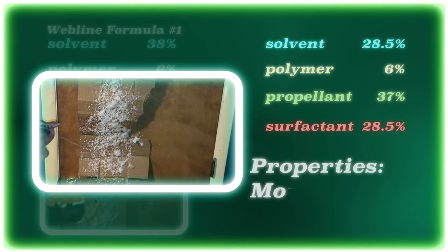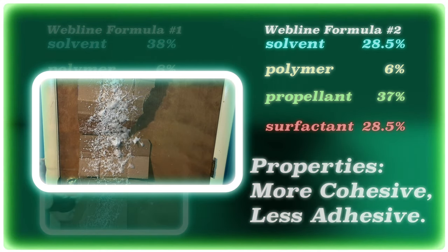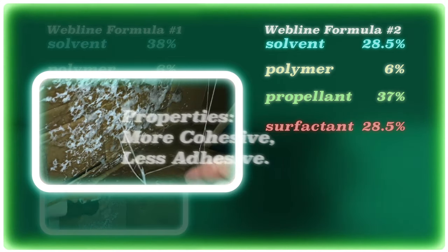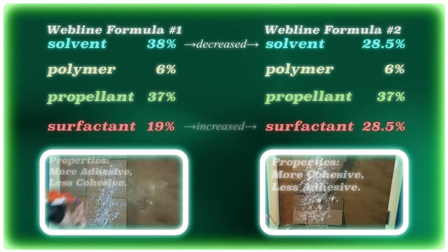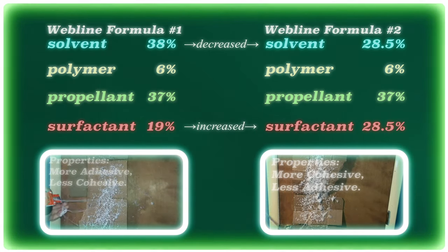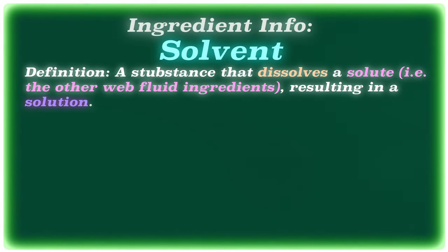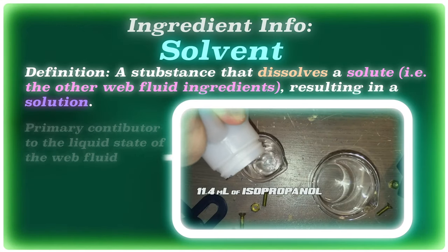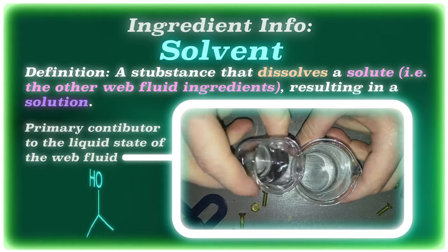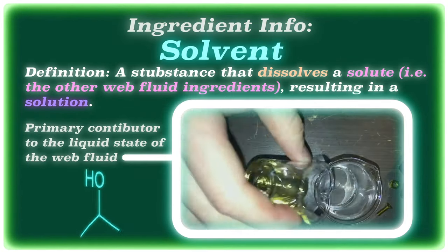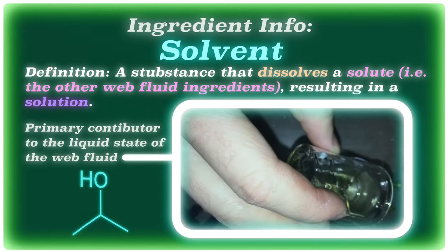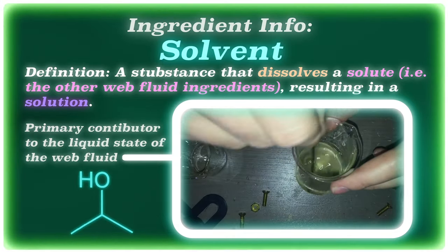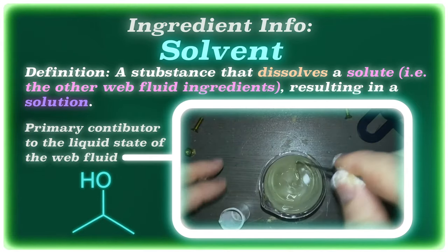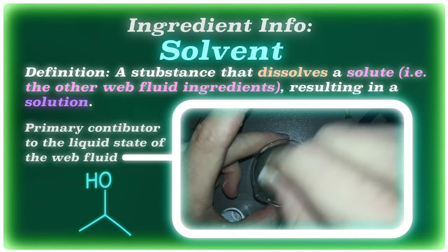I tested this web formula in this video, and it was clear the web lines were slightly stronger. Having the same amount of solvent and surfactant seemed to balance adhesion and cohesion. Why is this? Well, a solvent is what makes the web fluid a fluid for the most part. While the propellant also has some absolutely necessary dissolving properties, it must act together with the solvent in order to fully dissolve the polymer. Now, polymers are difficult to dissolve, so finding a solvent for a particular polymer can be tricky. In this case, it just so happens that polymethyl methacrylate will dissolve nicely in isopropanol, and that solution dissolves nicely in tetrafluoroethane, even when the surfactant is added.